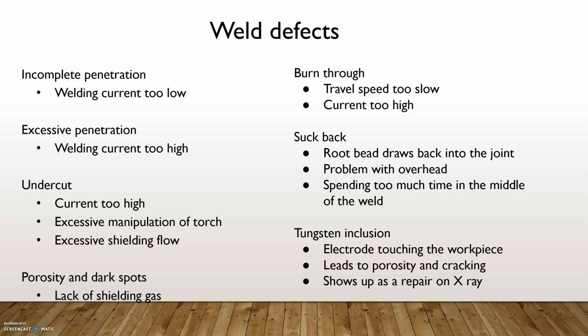Burning through is from going too slow or having too much current. Suck back is pretty common. That's usually from the root bead. The root bead draws back into the joint. This is a problem with overhead because of gravity. If you spend too much time in the middle of the weld and you're not putting enough filler metal in the weld, it's going to take material from the root pass and suck it towards the torch. And then you're going to have a concave inside of a joint, which is a defect.